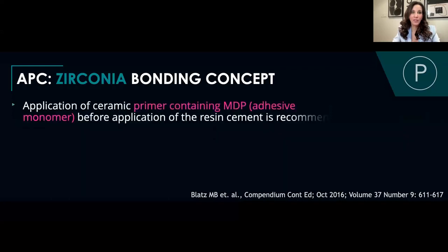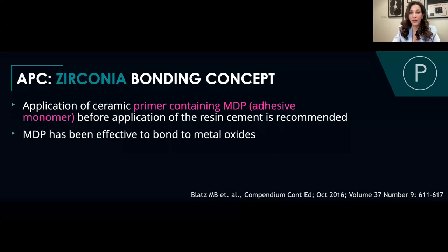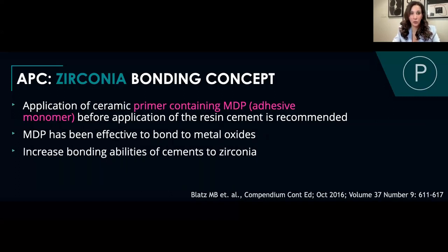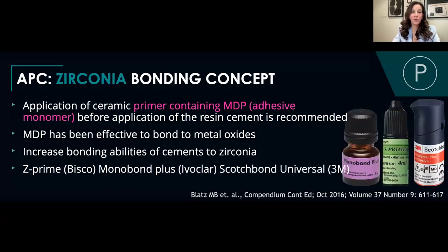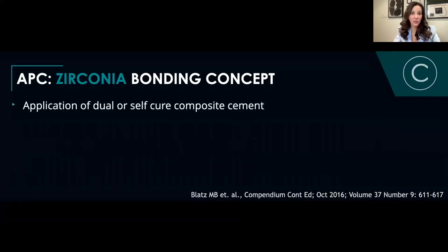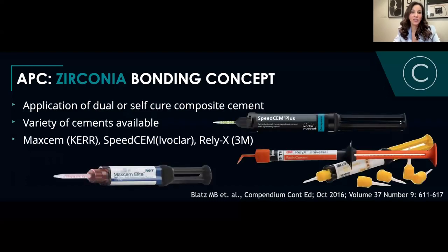P is the primer. And remember, we talked about primer, application of a ceramic primer containing MDP before application of the resin cement is recommended. Now, MDP has been effective to bond to metal oxide, and it increases the bonding abilities of cements to zirconia. And some examples of primers are Z-Prime or Monobond Plus or Scotchbond Universal. Now, this is recommended, but it's not mandatory because our cements, the C part of the equation, a lot of them contain MDP primers in them already, but it's not wrong to additionally prime your restoration if you wanted to. So that's P. The C is the application of a dual or self-cure composite cement, and a variety of cements are available, and these are just some of them. So Maxcem, BisCem, SpeedCEM, or RelyX. So these are just some examples.